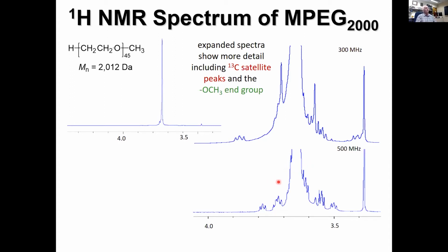So what we realized was you have this peak right here. If we say 0.97% C13 natural abundance is really 1%, so we have simple numbers. This peak here, I said, would be 180. This peak would be 3 if it was monofunctionalized. This peak here, or this peak here, would be roughly 0.5% of this peak, that is, this would be 0.9. This stuff in here would be 180, and this would be 3.